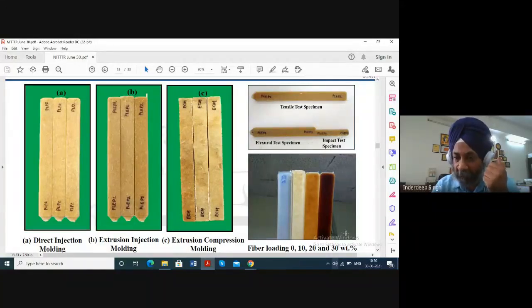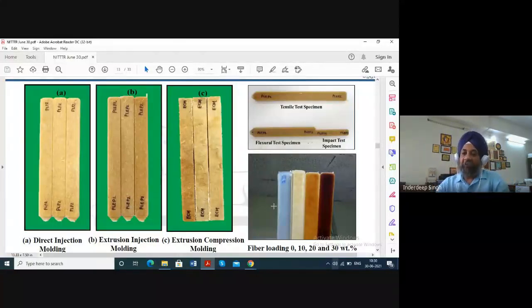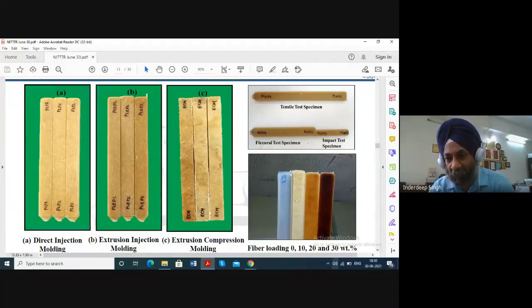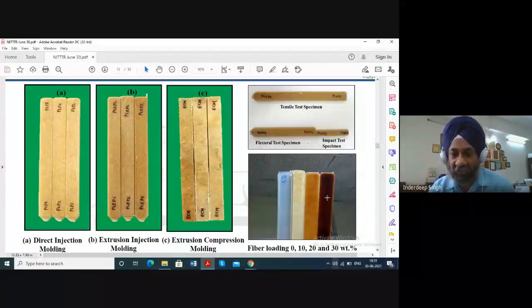And these are the other images which show how the samples look when you add the fibers. In the first case, a purely white sample, there is no fiber. In the second one, 10% fibers by weight, then 20% and 30%. At 30%, it gives a completely wooden look. And sometimes it becomes difficult even to recognize whether it is a wooden product or a natural fiber-based composite product. So these are the samples that we are able to make.